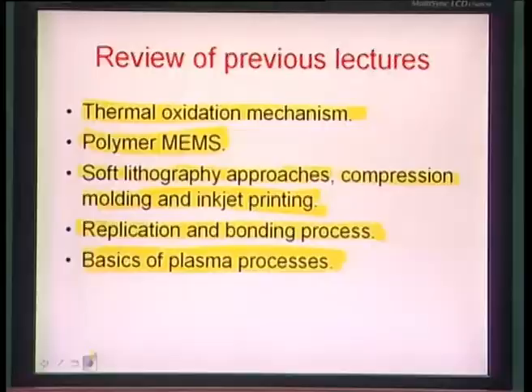or impedance. And for the very fact that the plasma system is a non-homogeneous material with different dielectric constants, you never know how the impedance would vary, and therefore you always have to have some kind of a matching network in series so that the overall impedance can be made equal to the source resistance, so that you could pump out maximum power from it without getting things reflecting off at the source resistance end. Okay. So now let us look at how this RF plasma is created, generated and sustained, and what are the basic differences in this case from the earlier used DC glow discharges.